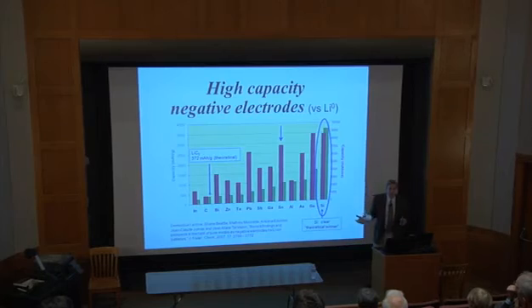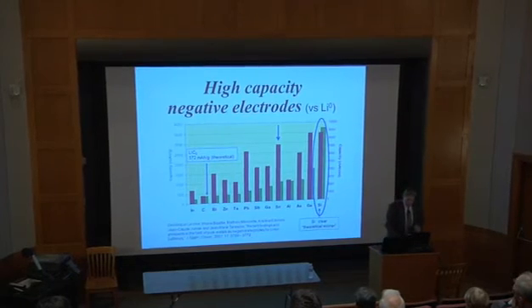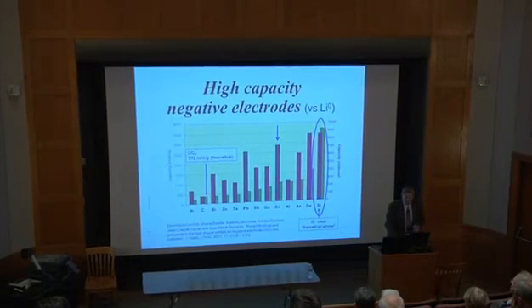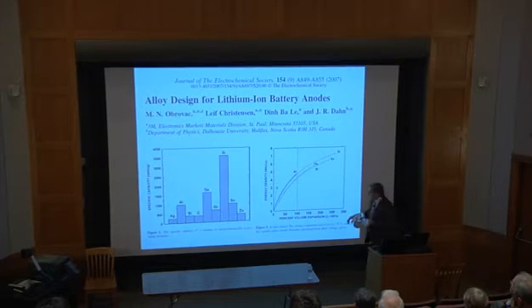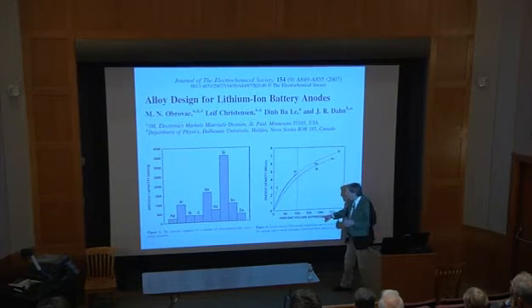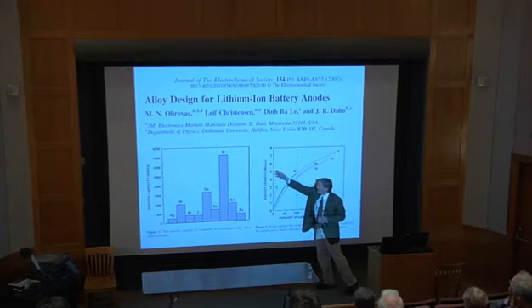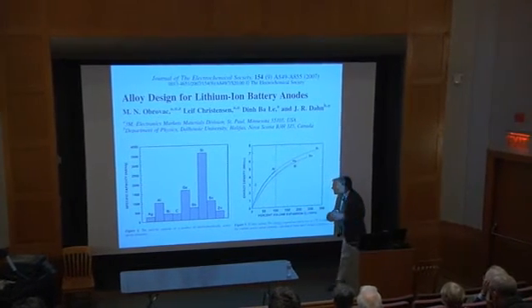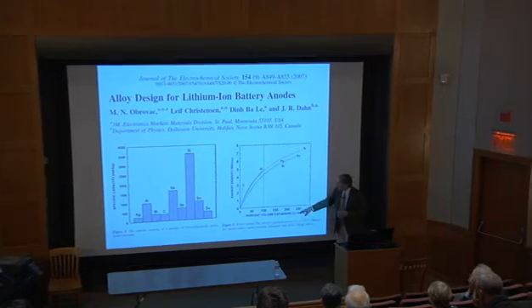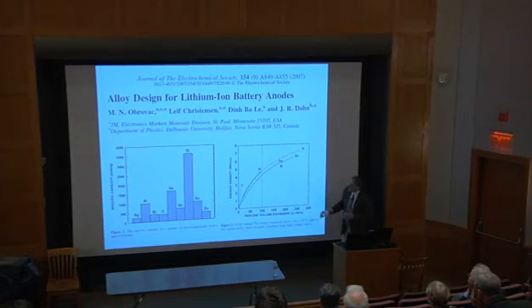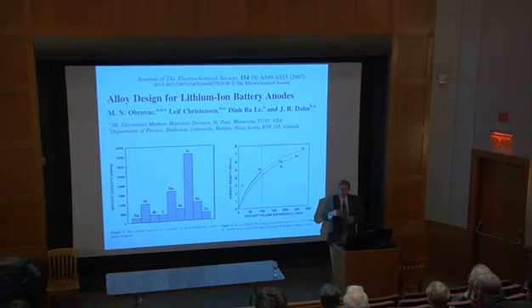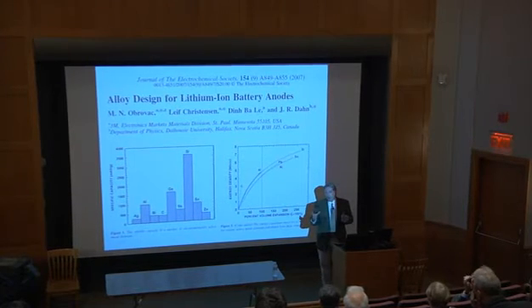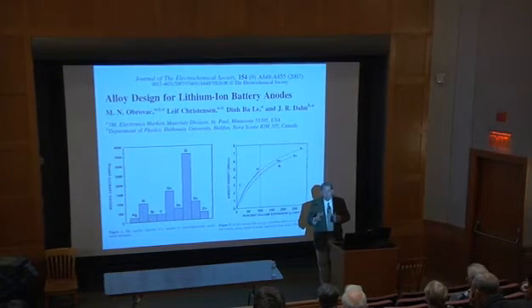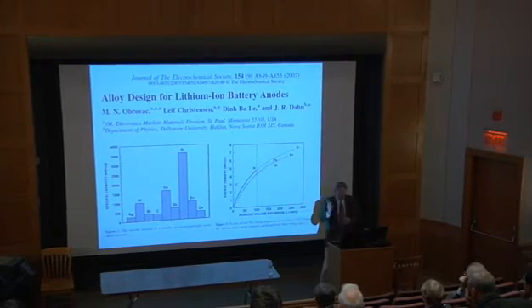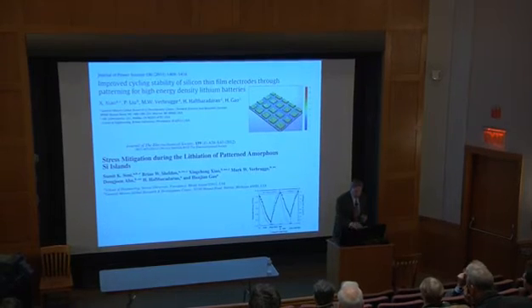It's 4 times higher. The challenge is that with silicon and many of these other systems, tin as well, basically the more you put in there, so the higher energy density your cell gets with these negative electrode materials, what you see is greater and greater expansion to up around 300% for the silicon system. You get enormous stresses built up in your particles, and all of those cracking and other phenomena associated with new solid electrolyte formation become something you've got to manage. And there are ideas for that I'll touch on just a bit.